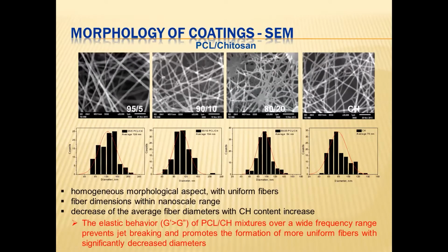For the PCL chitosan mixtures, the coating had a homogeneous morphological aspect with more uniform fibers, with fiber dimensions in the nanoscale range. The average diameter of the fibers decreases with increasing chitosan content from 124 nanometers down to 80 nanometers in the case of pure chitosan. In correlation with the results of the rheology study, the elastic behavior of the PCL chitosan mixtures prevents jet breaking and promotes the formation of more uniform fibers with significantly decreased diameters down to nanoscale.